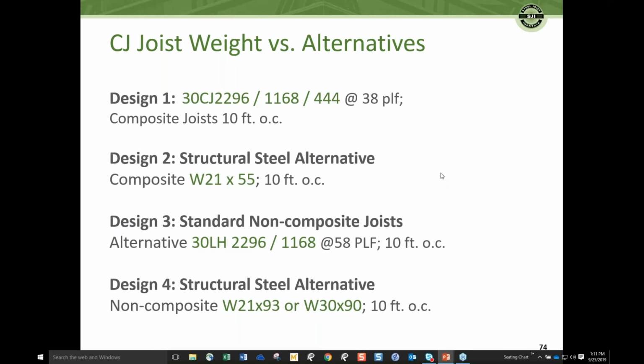I looked at comparing the weight of that particular design, which was our 30 CJ 2296, with several other alternatives, as we had determined that joist weighed 38 PLF. If we looked at, say, a 21 by 55 beam on 10 foot, and we were needing to run the HVAC below, that is going to be heavier. It's 55 pounds versus 38 PLF. If we looked at a non-composite joist with the same depth and load, we would end up at 58 PLF, which is considerably heavier than the 38 PLF. And if we were to look, say, at a non-composite beam, which people typically would not use, but if you had a 21, you would have to go to, say, a W21 by 93 or W30 by 90, which is much, much heavier. So composite joists on these longer spans will almost always come out with much lower weights and lower cost.